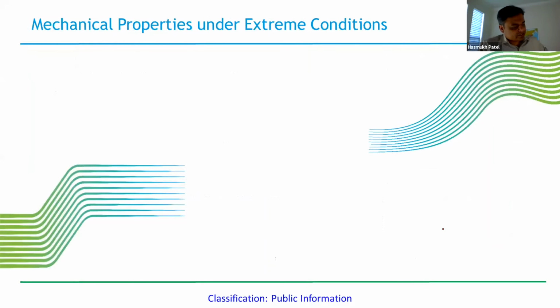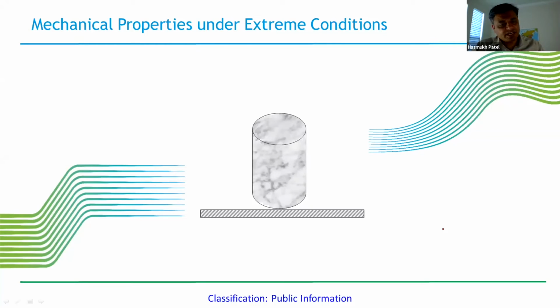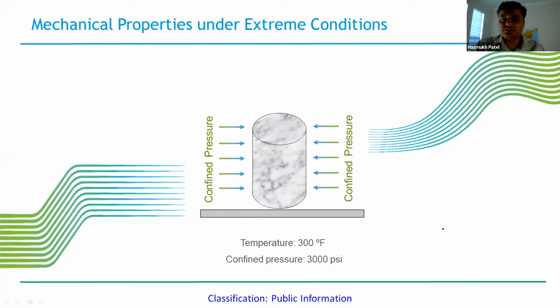The most important thing we were focusing on is the mechanical properties. What we eventually want to achieve is better mechanical properties when adding polyrotaxane into the cement matrix. Here you can see we made a cylindrical sample of the cement and measured the mechanical properties under these conditions. For example, we have a confined pressure of 3000 psi on the cement, a cyclic stress for the Young's modulus measurement, and a uniaxial stress for the compressive strength.